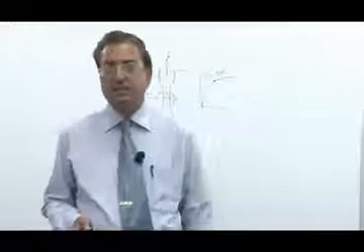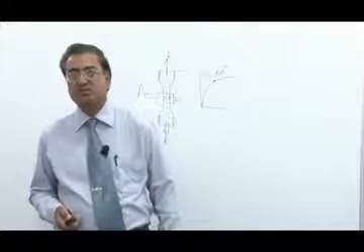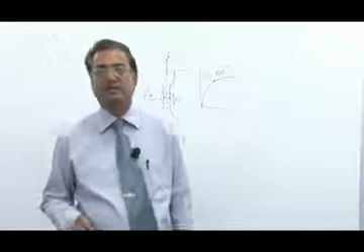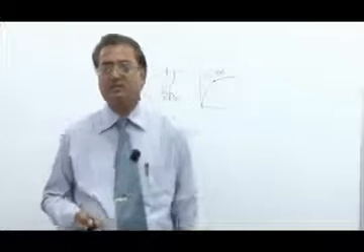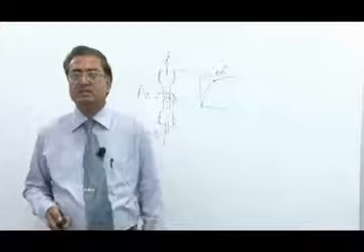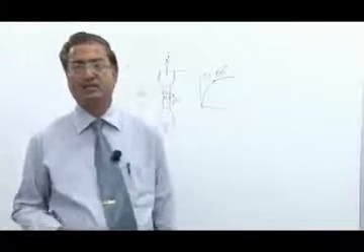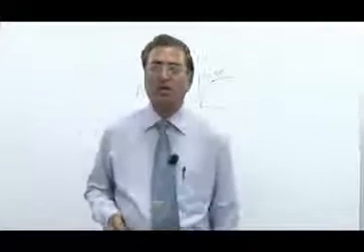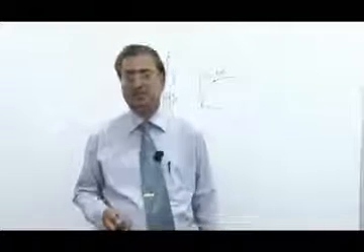One can also see the stress distribution in necking. Usually this plot shows the stress equation where there is a complex triaxial state of stress in the necking region for this mild notch steel, and one can also calculate the average true stress at the necking point. This is much higher than the stress that would be required to cause normal plastic flow, due to stresses in the width and thickness direction.